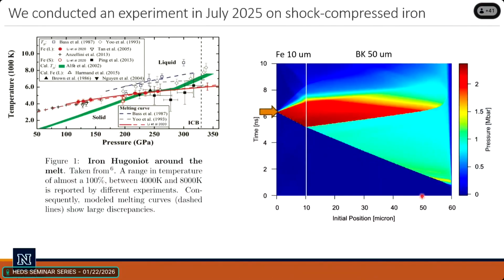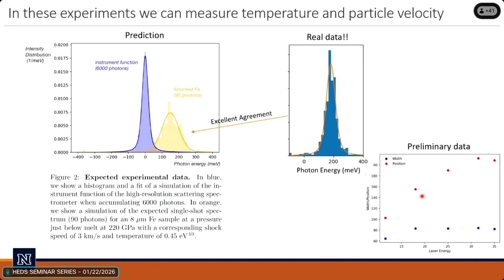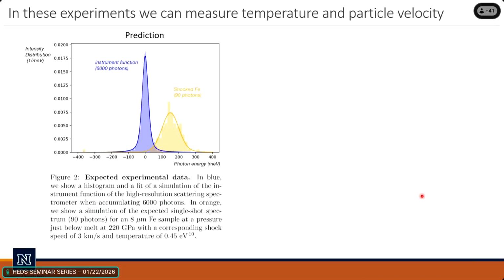The shock goes into the iron, and then we measure the temperature at the breakout point. So we can measure the temperature of the shock state right here. And it works pretty well. What you get there, a thicker target means more photons scattered. So there we have more flexibility with the materials that we can use, and that's why we're able to use iron. And we were getting hundreds of photons per shot, so it was really good.